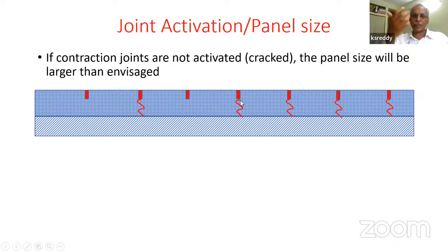So those of you who had the opportunity to examine failed concrete pavements, if you noticed whether there is a crack that has formed below these grooves, you would find in many cases there was no crack below the groove. That may be because the joint spacing that you consider, 4.5, is too small, because you are putting a plastic sheet there. The aggregate that you are using may be of such quality that its coefficient of thermal expansion may be small. So the expected thermal stress, which would crack the slab at 4.5 meter spacing, is not getting mobilized. It can only crack the slab at 9 meter spacing. So if that were the case, what you are actually creating is a 9 meter long slab. Similarly, if the longitudinal joint doesn't crack, you might actually create a 9 meter by even 7 meter slab, even a wider slab, maybe a 10 meter slab.